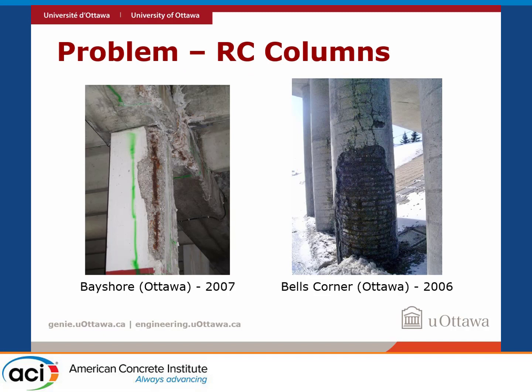It creates problems in reinforced concrete that was not designed with a large enough concrete cover, or where the material is not of good quality in terms of low water-cement ratio and high strength. So usually the problems start to occur on aging infrastructure that has been in service for at least 30 to 40 years. And I have an example here of reinforced concrete columns. The one on the left is a parking garage in Ottawa that was eventually demolished and rebuilt because the membranes of the slabs were not properly maintained.